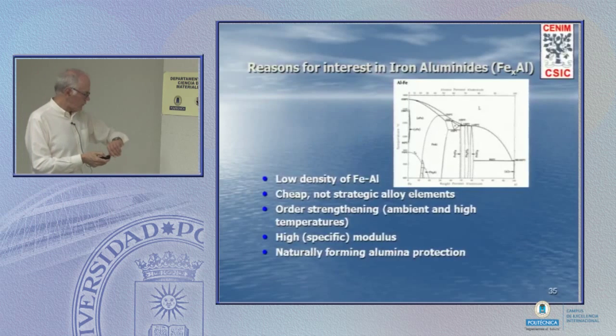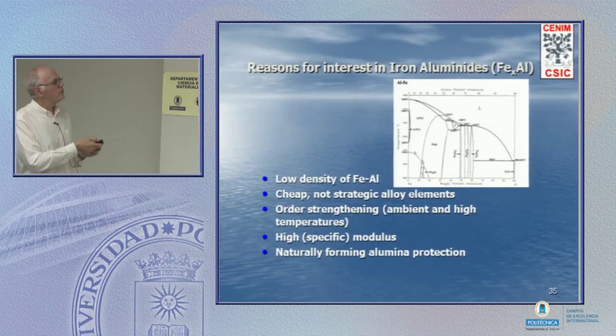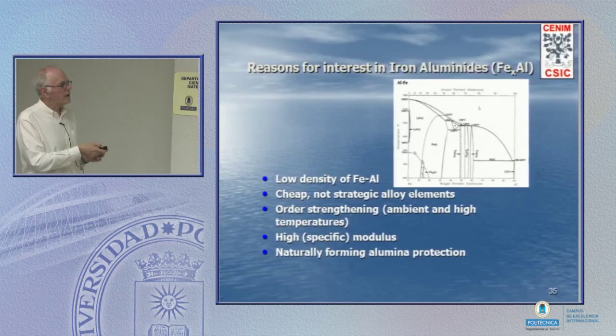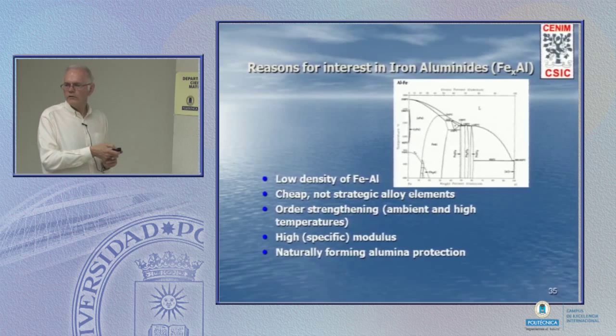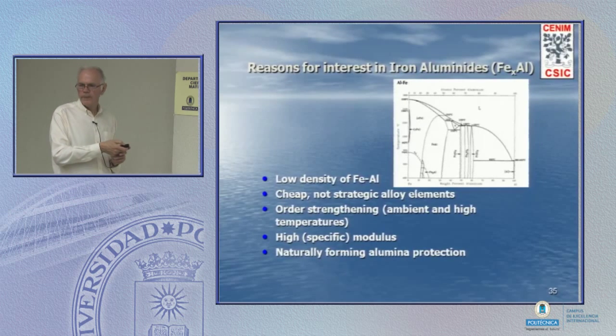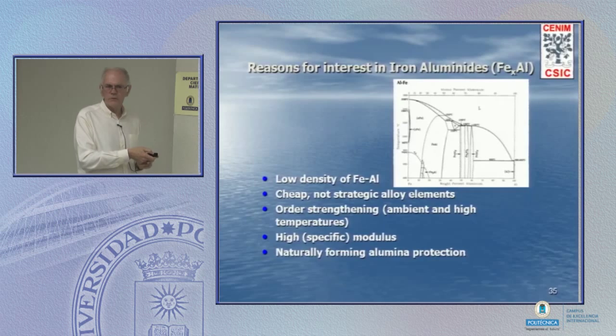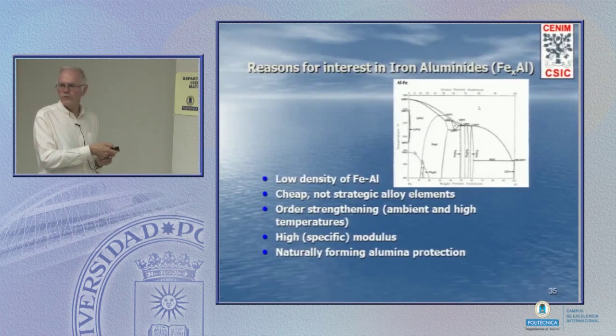Okay, let me jump to the third family that I want to talk about, the iron aluminides, iron aluminium. Here's the FeAl phase region, ordered all the way up to the melting point. Here's the Fe3Al phase region, ordered up to about 550 Celsius. Now, we've got steel with a lot of aluminium, so it's a very low density steel. These form a natural alumina that protects, so you don't need lots of chromium or lots of nickel to get the properties. They're very cheap in terms of basic alloying additions. We've got order strengthening, and we've got a high specific modulus. The modulus is a little bit higher than steel, and the density is much lower.